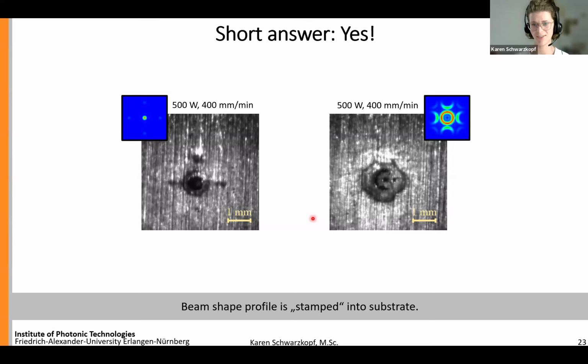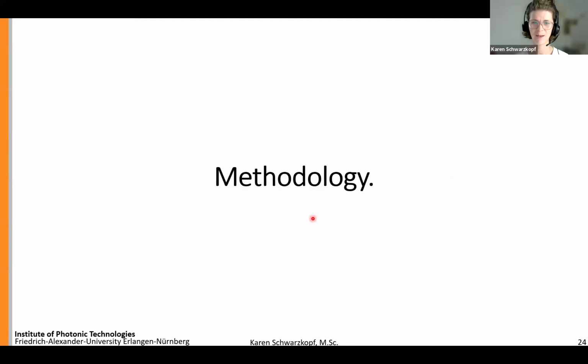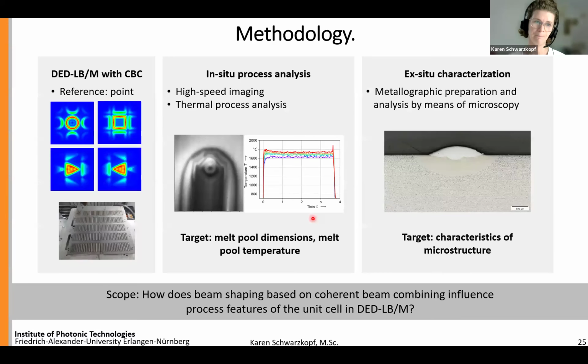And since we are a research institute, this answer is not sufficient for us. Therefore, we employed the following methodology to answer the research question. We were comparing 5 different beam shapes, which I will go into detail on the next slide. We were then using in-situ process analysis, basically high-speed imaging and thermal process analysis, to understand how dynamic beam shaping is influencing our melt pool dimensions, for instance, the melt pool area, but also the morphology, and also the melt pool temperature. As the next step, we wanted to correlate these findings with ex situ characterization, like for instance, the microstructure, but also the resulting hardness.